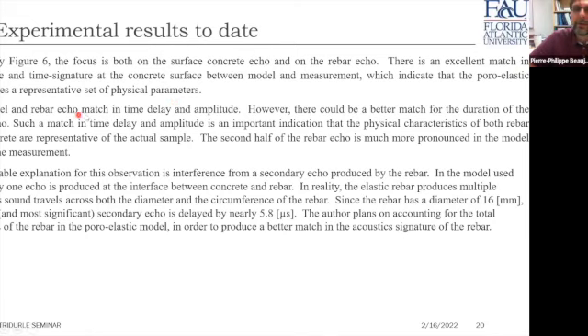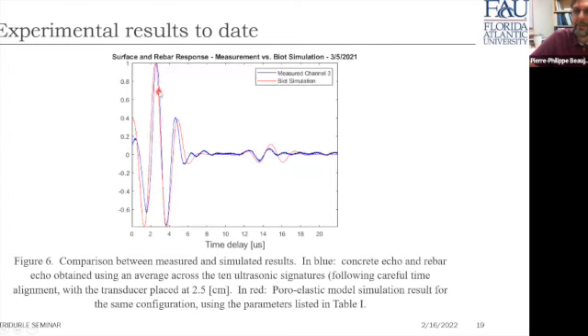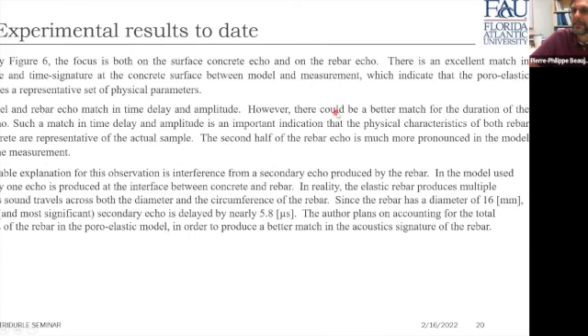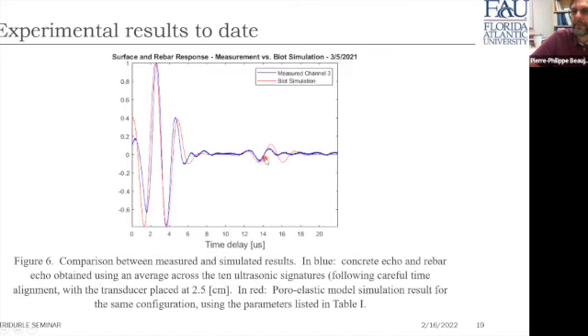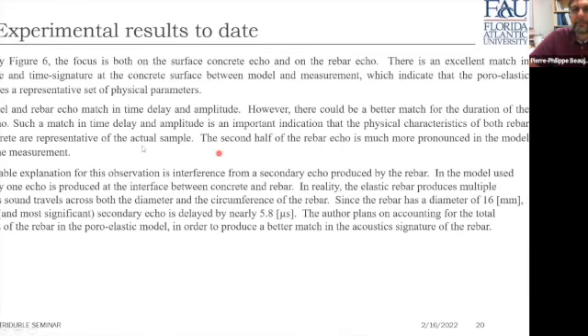Now, the model and rebar echo match in time delay and amplitude. As we can see over here, there is a good match between the red and the blue in both cases, but there could be a better match for the duration of the rebar echo, which is over here. We notice that the simulation indicates that the rebar echo should last a little longer and should be just a tad stronger. Such a match in time delay and amplitude is an important indication that the physical characteristics of both rebar and concrete are representative of the actual samples.